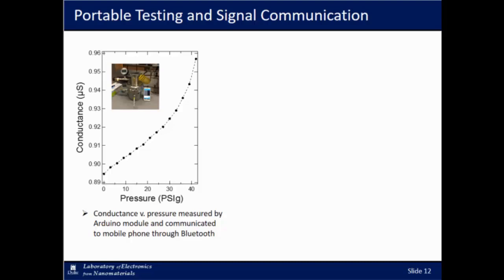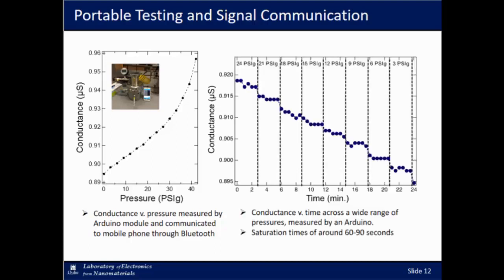So this data that you see here was all sent to a cell phone. Basically, as a proof of concept that this pressure sensor could be fully encapsulated in the tire and give the end user the data on the outside. Here's a little data of how the sensor works over time. So you see that the conductance saturates after about 60 to 90 seconds. So it's not quite immediate. There's some equilibrium time.